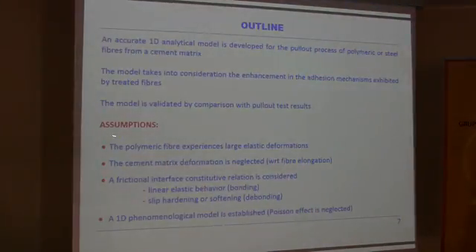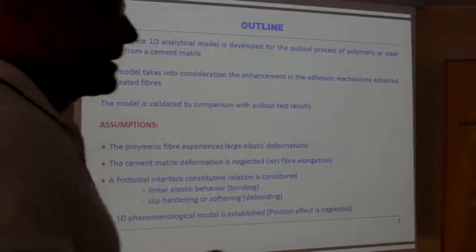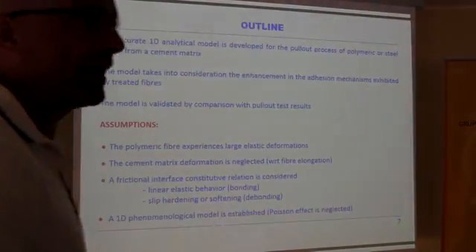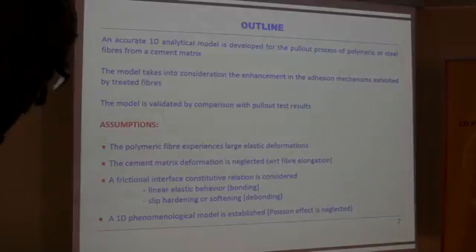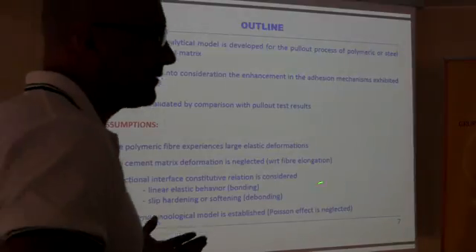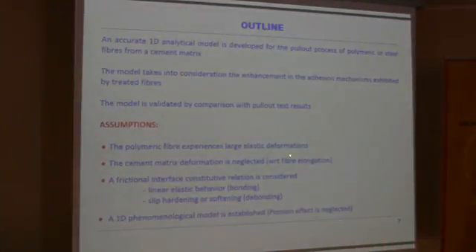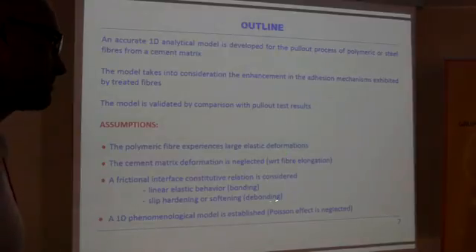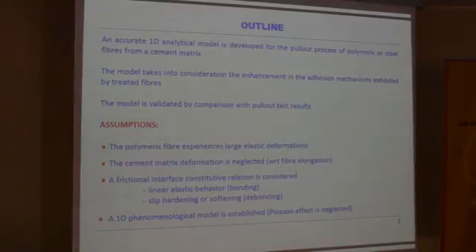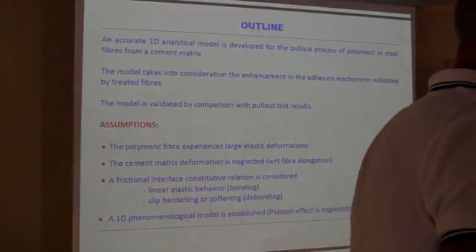The model is based on the following assumptions. The polymeric fiber experiences a large deformation, so finite deformation of the polymeric fibers, and for the matrix, the cement matrix, we neglect the deformation with respect to the fiber elongation. So the cement matrix is considered almost as rigid. However, we introduce a frictional interface constitutive model between the matrix and the fibers.